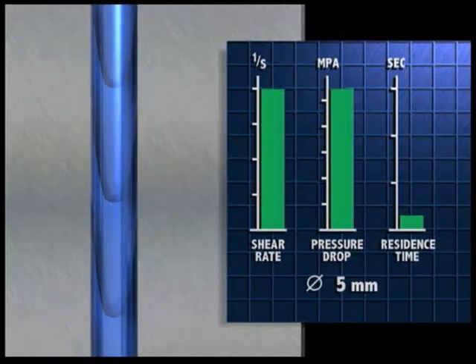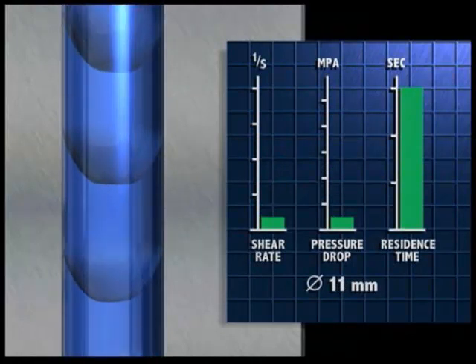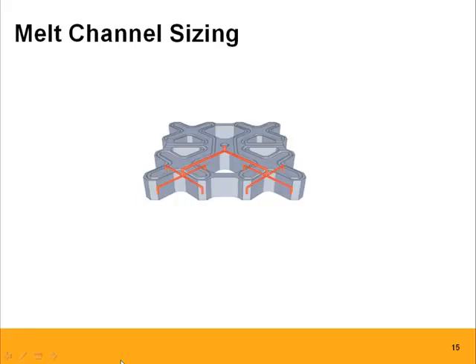As we go bigger, residence time will go up, shear rate will go down, and pressure drop will go down. Now when we optimize a system, we're trying to balance those. Because of course we still want to be able to fill the actual plastic part at the end of the day, and we don't want to have situations where you're pressure limited to fill the part. But if you come to us, for example, with a frequent color change application, we will pay a little bit more attention to shear rate versus the pressure drop within the limits of the machine, of course.